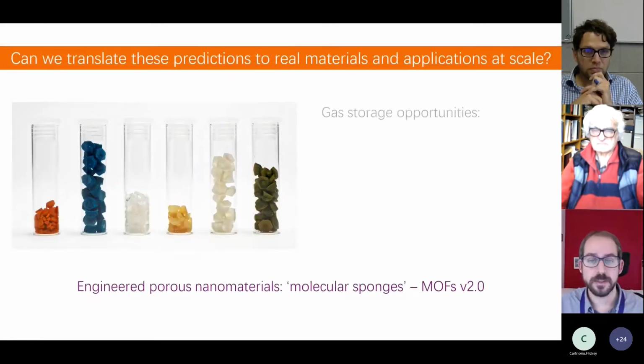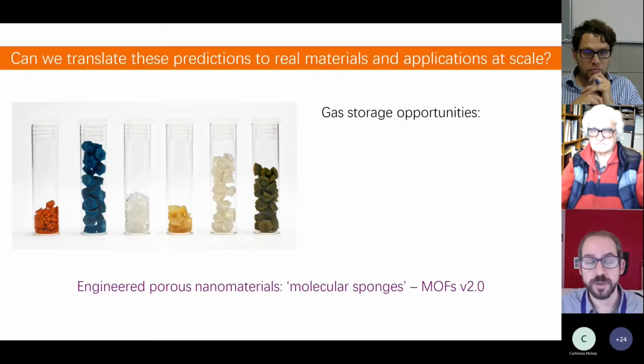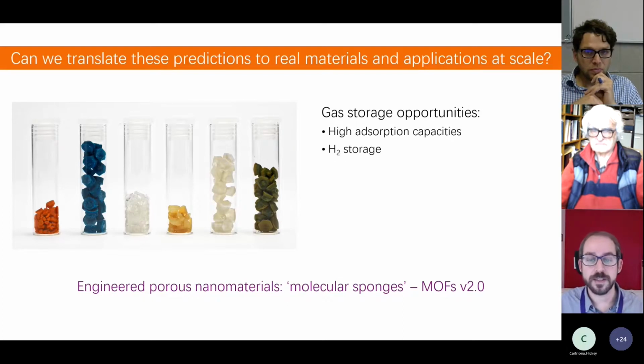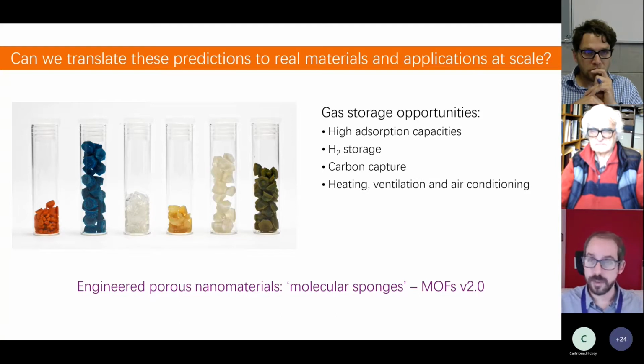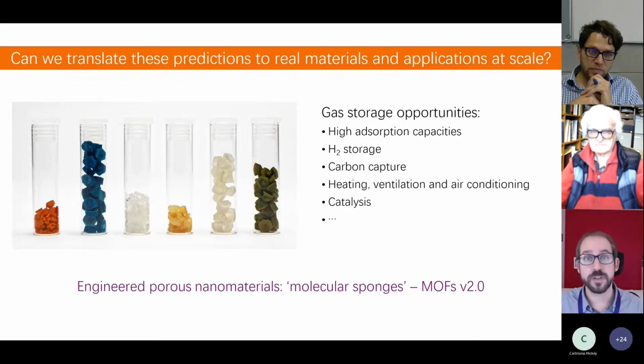The answer again is yes, and this is where we work with these engineered porous nanomaterials or molecular sponges, and we like to call these monolithic materials MOFs version 2.0, because this is something that can really translate all the volumetric capacities that we have been predicting in the lab or with the computers about these materials, but now using real densities, not the single crystal density, the theoretical density, but the real density of the materials we have developed. A lot of different applications, a lot of different possibilities with these materials.